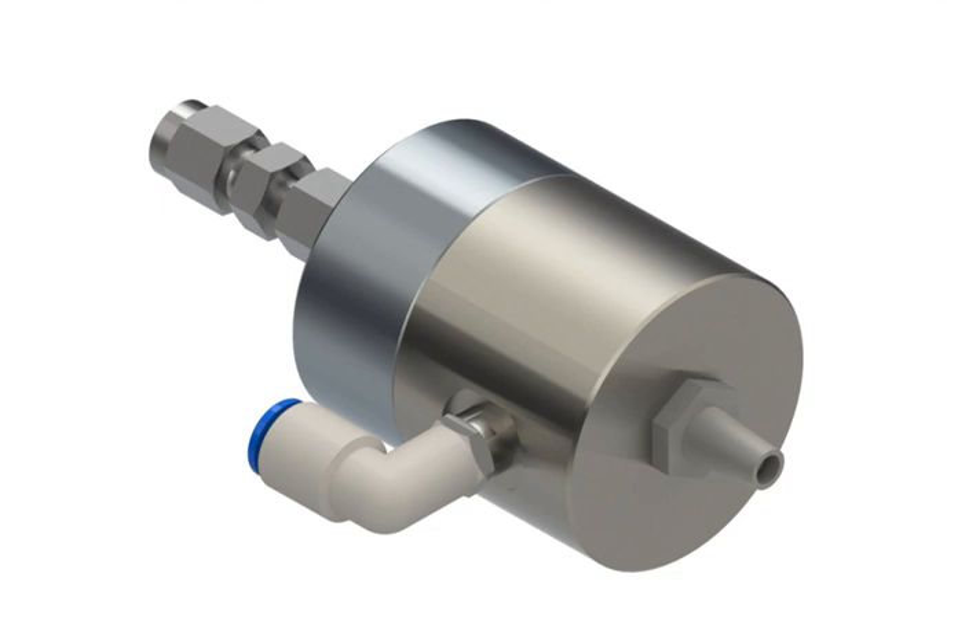When ultrasonic nozzles are used, the spray can be made to be as dry as necessary by the nature of the small and uniform droplet size, by varying the distance the droplets travel, and by applying low heat to the substrate such that the droplets dry in the air before reaching the substrate. Process engineers have finer control over these variables. Additionally, because the ultrasonic nozzle imparts energy to the suspension just prior to and during atomization, possible agglomerates in the suspension are broken up, resulting in homogeneous distribution of the catalyst, and in turn higher efficiency of the fuel cell.